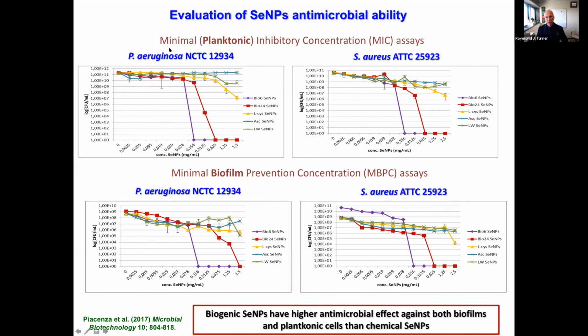So here's Pseudomonas aeruginosa, Staph aureus, two pathogenic strains, and we were able to kill off both planktonic and the pathogenic biofilm version with the selenium nanoparticles produced by the bacteria, not those that are chemically synthesized.